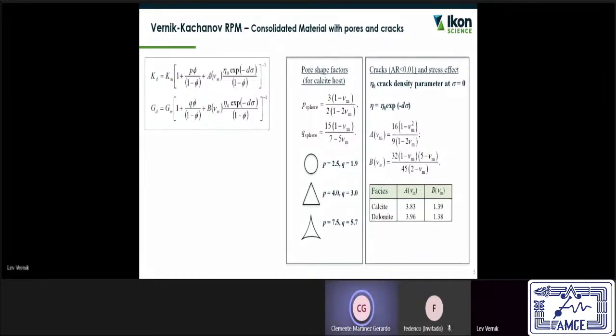Not assuming necessarily that. If the fracture is fully cemented, then you don't have a fracture. So if you have a fracture, it might have some asperities which might be cemented, and that will lead to a reduction in compressibility. And you will have to modify the crack density parameter, which is kind of an interesting thing by itself.